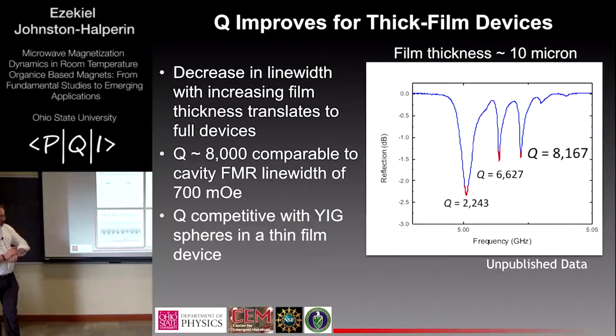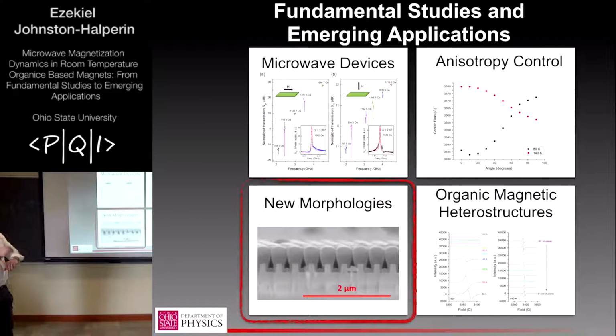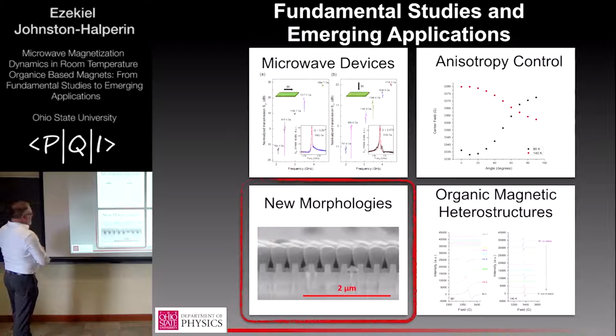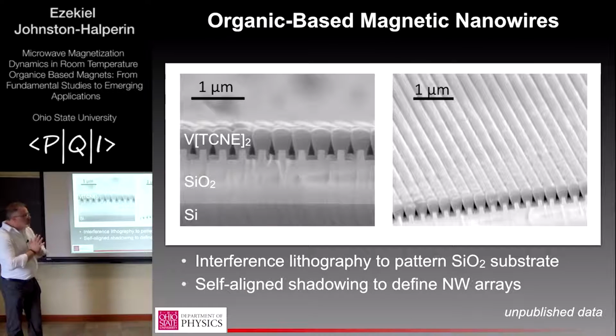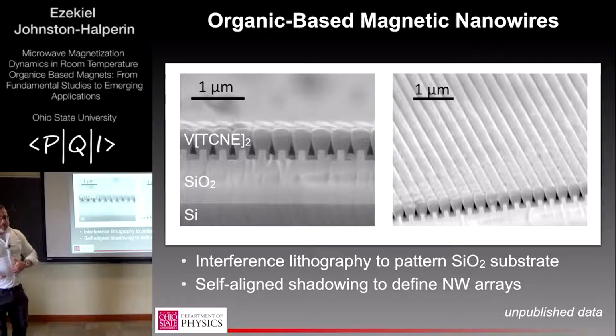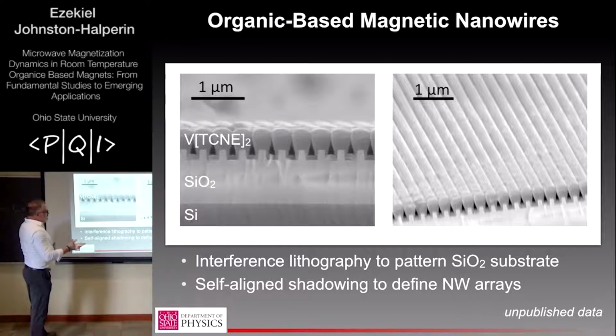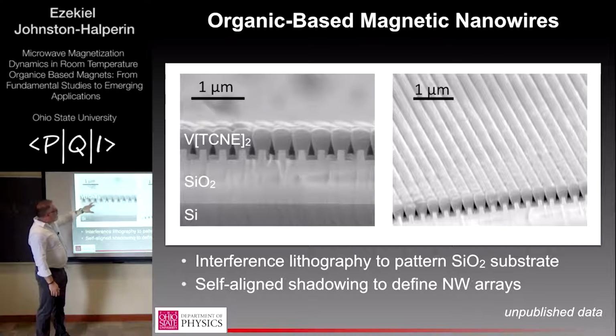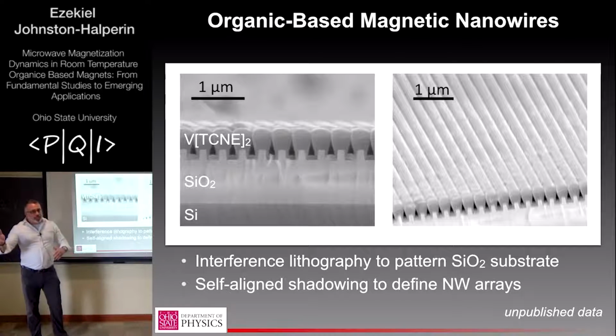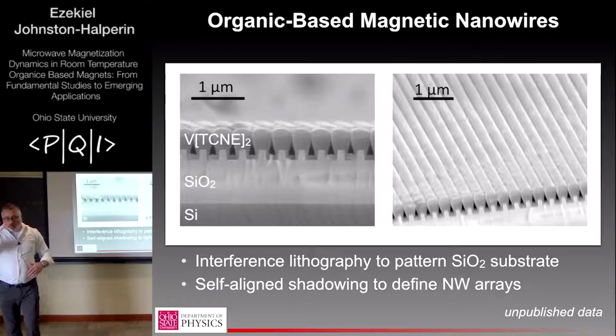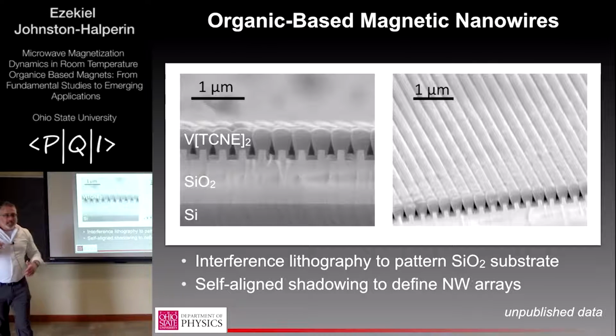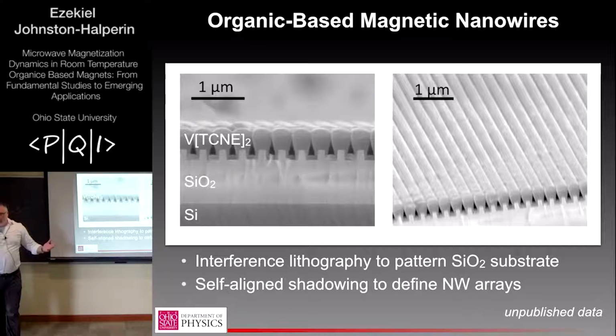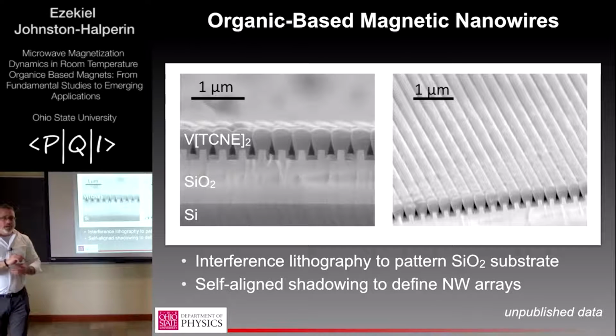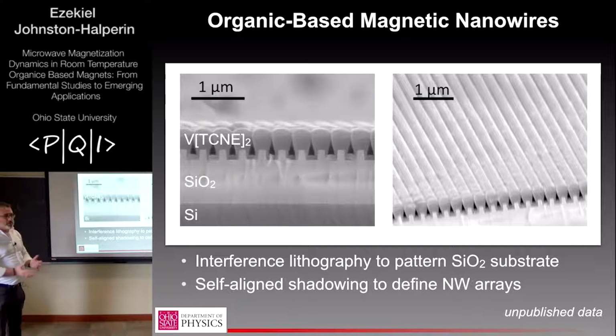So in a different direction, but one that has potential to circle back, we also have discovered really fascinating things about the morphology. Because this is a CVD deposition, it comes down conformally, and in collaboration with Georg Schmidt's group at University of Halle, we decided to try and make it corrugated, with the idea being that we would make a conformal film and then use the shape anisotropy of that corrugation to induce some in-plane magnetic anisotropy,